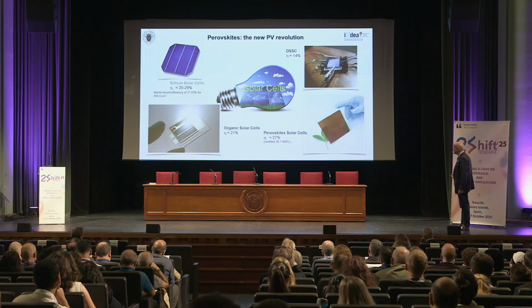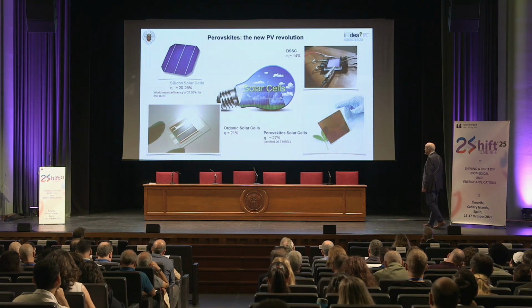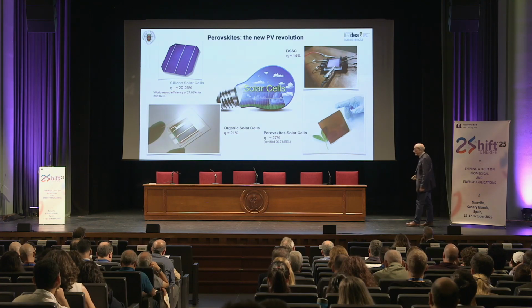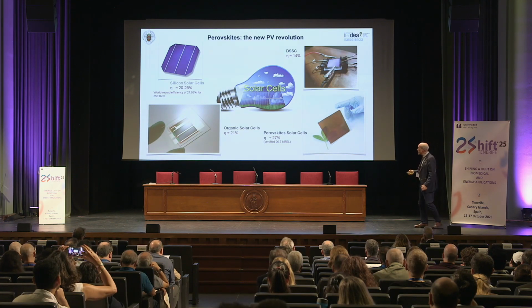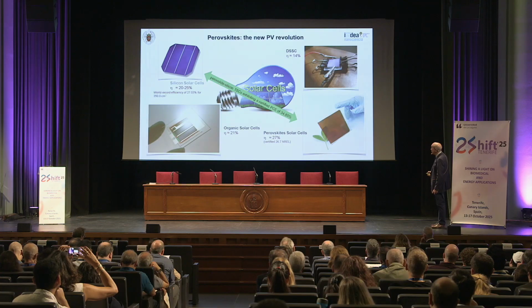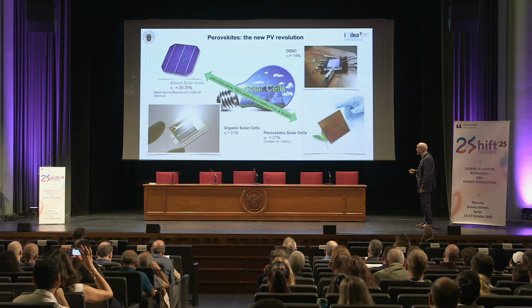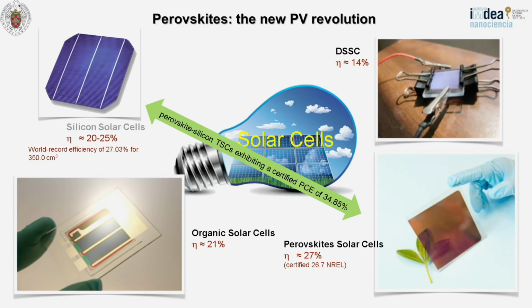And what about the perovskites? Recently was reported around 27% and was certified 26.7. So this is really interesting, and if you consider the possibility of tandem solar cells, including perovskites and silicon, efficiency close to 35% has already been achieved, which is quite interesting.